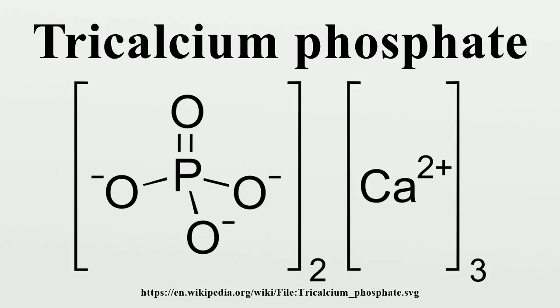Preparation of pure Ca3(PO4)2: It is generally believed that tri-calcium phosphate cannot be precipitated directly from aqueous solution. Typically, a double decomposition reaction involving a soluble phosphate and calcium salts — 2HPO4 plus Ca2+ — is performed under carefully controlled pH conditions. The precipitate will either be amorphous tri-calcium phosphate (ATCP) or calcium-deficient hydroxyapatite (CDHA).